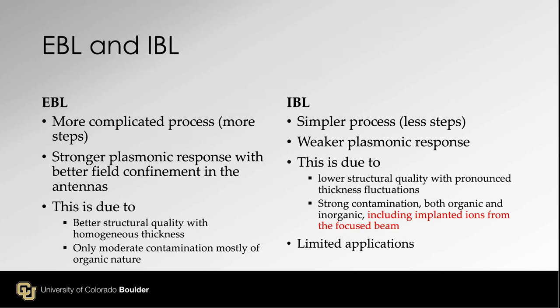Now, IBL, simple process, less steps. However, the final product, the antenna, showed weaker plasmonic response. This is what they didn't want. This is due to lower structural quality with some thickness fluctuation within the metal piece and strong contamination, both organic and inorganic, including implanted ions from focused beam, in this case, the gallium ion implantation. Implantation can change electronic structure of the material.